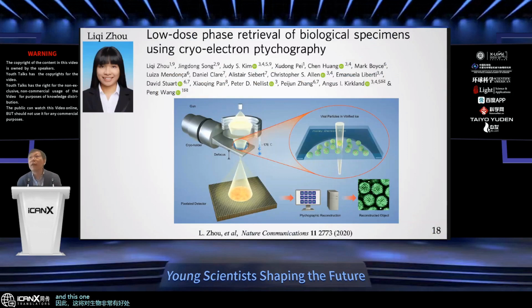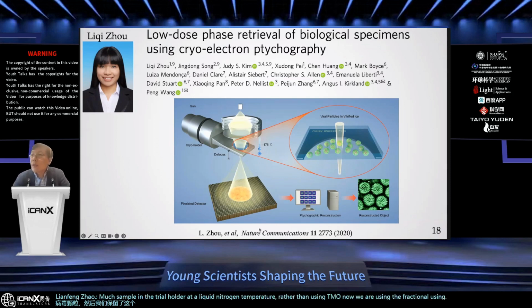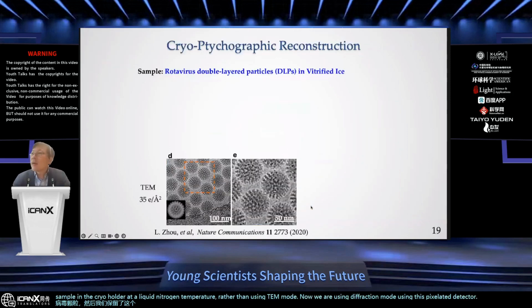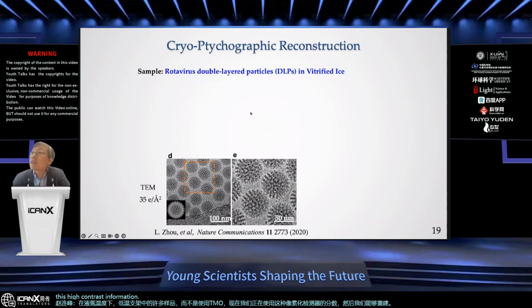And this one is our first implementation in cryo biological imaging using electron ptychography. As you can see here, we prepared the sample in the standard cryo method, and this sample is a vitrified viral particle. We kept this sample in the cryo holder at liquid nitrogen temperature. Rather than using TEM mode, now we are using diffraction mode with this pixelated detector, and we are able to reconstruct this high contrast information of the viral particles.